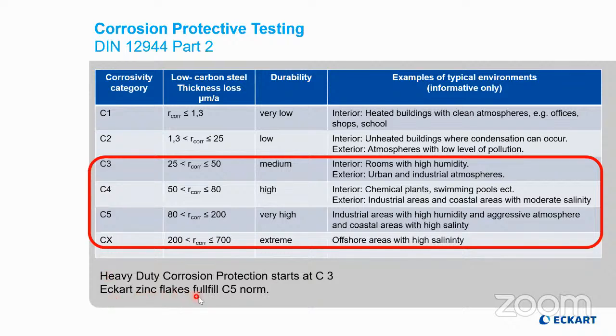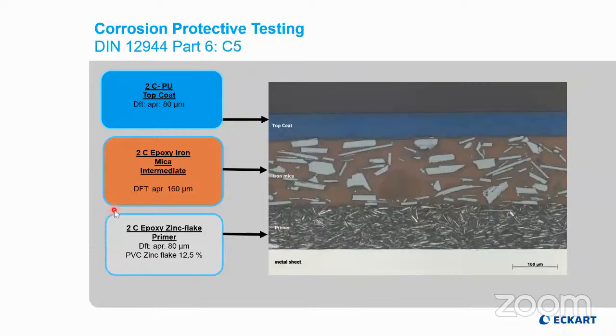With our ZincFLAKEs, we have proven we fulfill the C5 norm at least, and this can be achieved by a film build like this. And you see here a cross-cut section through a typical corrosion protective system. You see the steel substrate. You see the epoxy primer with roundabout 12.5% PVC ZincFLAKE at a dry film thickness of 80 micron. On top of that, and that is no change to previous procedures, an intermediate containing micaceous iron oxide at a film thickness of 160 micron, and on top of that, finally, an 80 micron two-component polyurethane top coat.